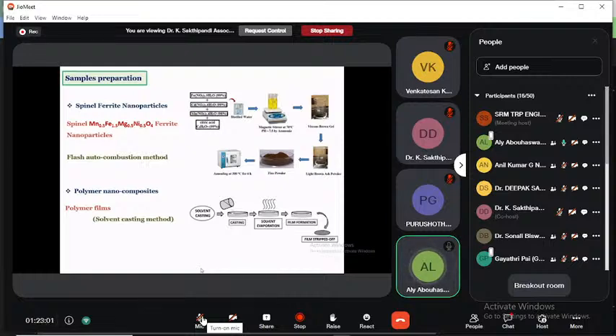This slide shows how we prepared the sample. The spinel ferrite we prepared by the flash auto combustion method, as seen in the first picture. After that, the polymer film was prepared by the casting method, as shown in this figure.